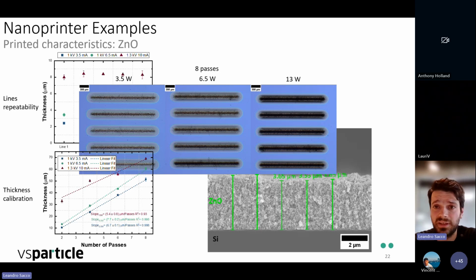Here we can see a set of lines that we printed using zinc electrodes. Then we deposit zinc oxide material at different powers. Essentially, with the nanoparticle generators, you can control three parameters, I would say, in principle: the potential, the current, and the gas flow. So here we just change the power. As we increase the power, we expect to have more material deposited, and then we deposit 5 identical lines on these substrates, and then we measure the thickness of this material.